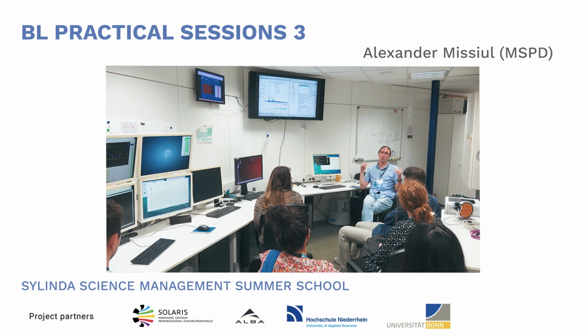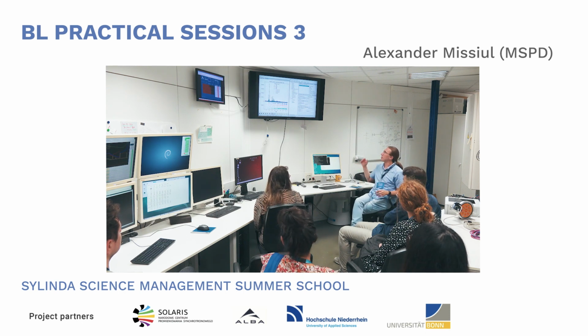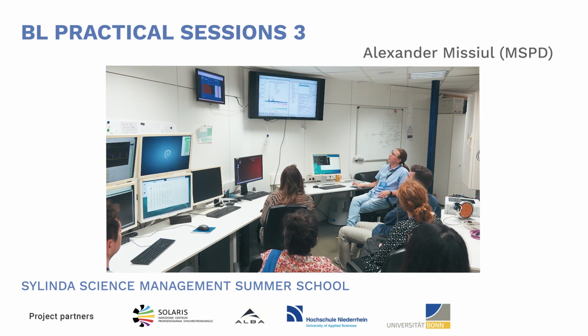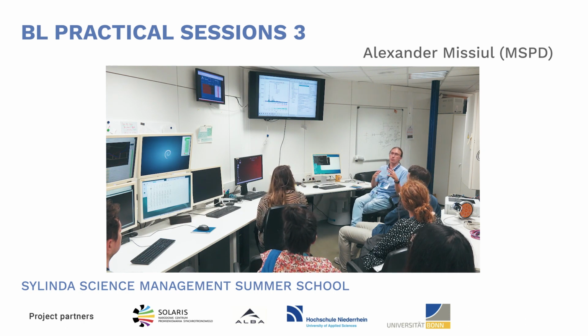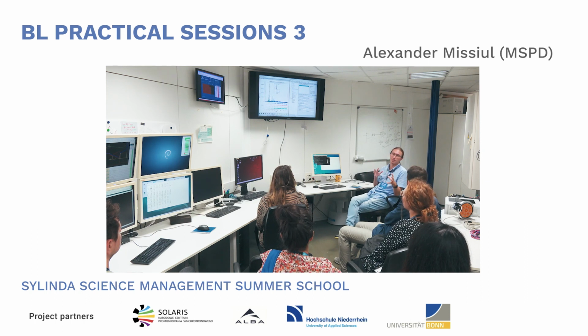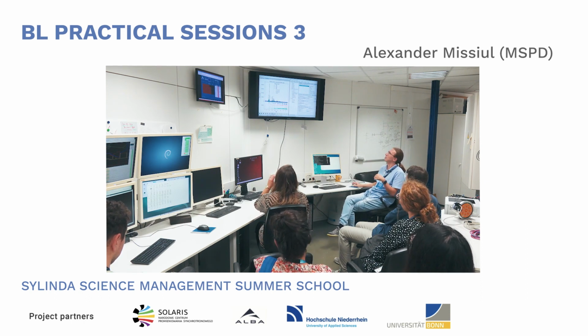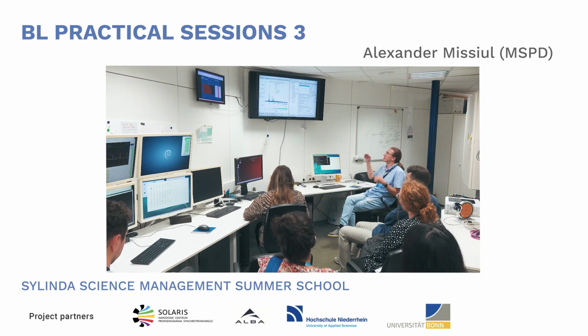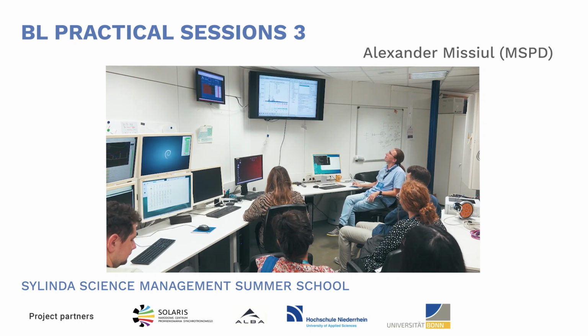Sometimes for atoms you also have to go step by step, starting from heavy atoms that affect more, and then going to lighter atoms that affect less. And then you might need to add more parameters, like, for example, preferred orientation. If your material is very anisotropic, it might not be really randomly oriented, and you might need to take these parameters into consideration. So then it depends. You go more and more.